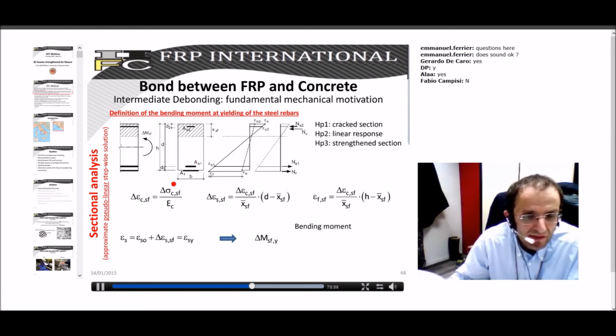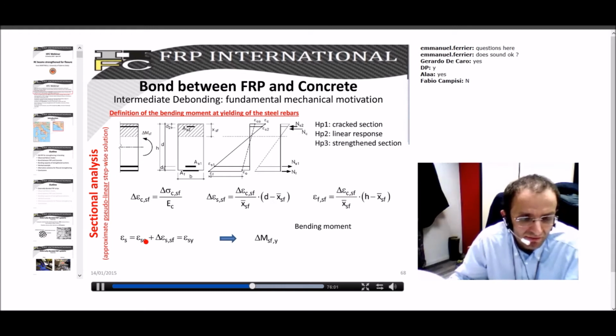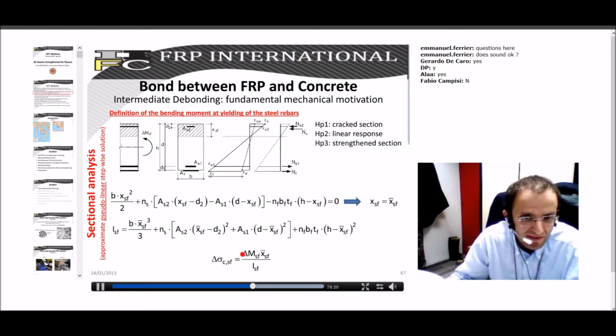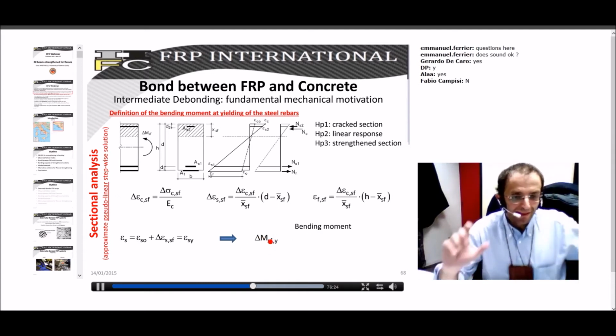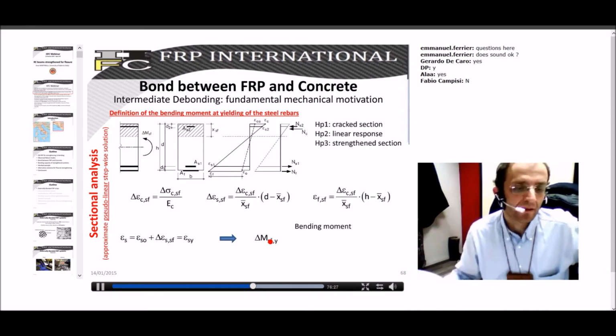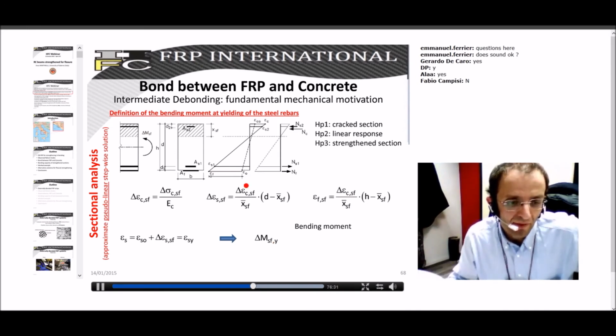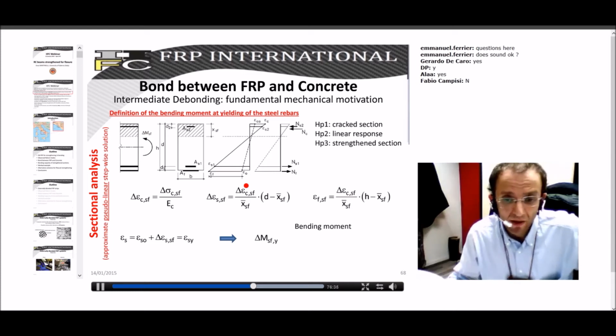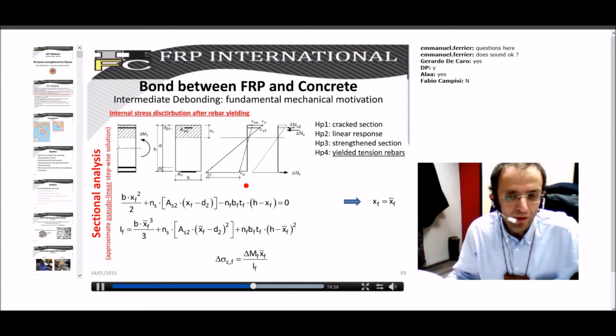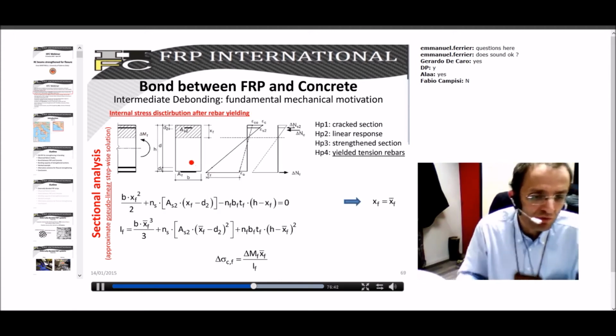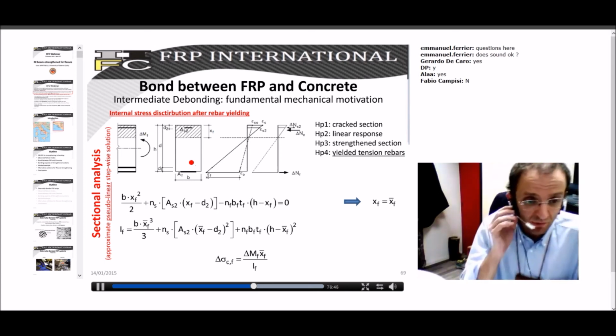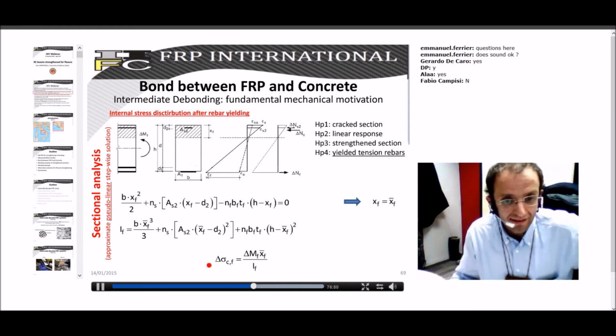But the yielding of the internal reinforcement is obtained when the initial strain of the internal bars plus the one developed by means of the moment increment are equal to epsilon sy. If you solve this equation, by introducing this delta epsilon with the moment explicitly inside it, you obtain the moment increment resulting in the yielding of the internal steel reinforcement, which means that for further increase you will have another section with no contribution from the steel reinforcement, which is actually yielded, so it cannot contribute to further delta f, the delta m.